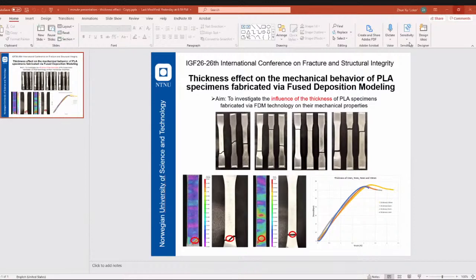Yes, was any correlation found between failure modes and stress and strain curves? Did you check the failure modes on the samples, like if they are failing from shear, or is it always perpendicular to the loading direction? According to the image I have here, as you can see my cursor here, this is the specimen for 1 millimeter thickness. Two of them failed based on the raster angles, and all of the others failed perpendicularly.